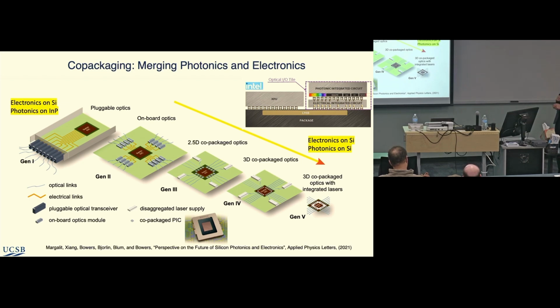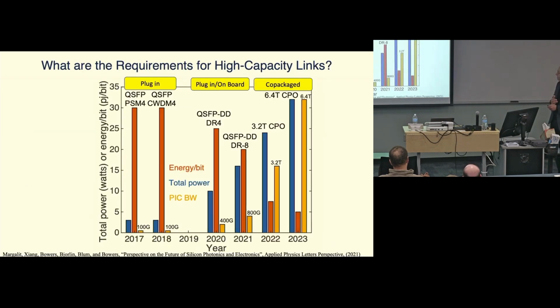Not workable. Once you head here, now you've got a few microns between the transistor and the modulator, so there's no 50 ohm transmission lines — it's just a very small amount of capacitance. In fact, the capacitance of through silicon vias is too high at 200 terabits, so this is just very, very short interconnects. At some point you'll have this 3D co-package with integrated lasers. Intel's doing that today, but they're the only one that's gone that far.